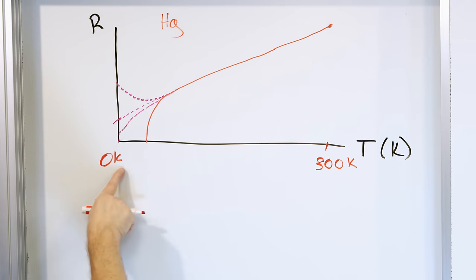And the way you apply this pressure, actually, you don't just use a vise, you have to have a diamond. Diamond is the only material that can withstand the pressure. You have a diamond anvil with sharpened points, and then you put the superconductor between it, and you apply this incredible amount of pressure while you cool it down, and it turns out that they can get a superconducting critical temperature up to 250 Kelvin, right?